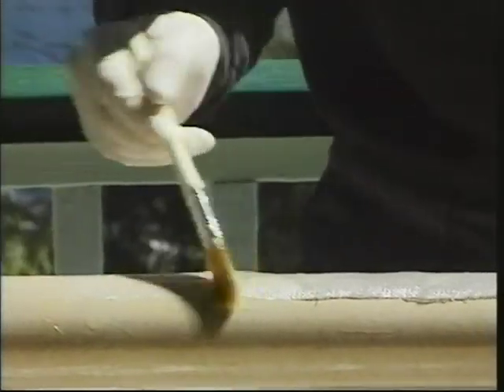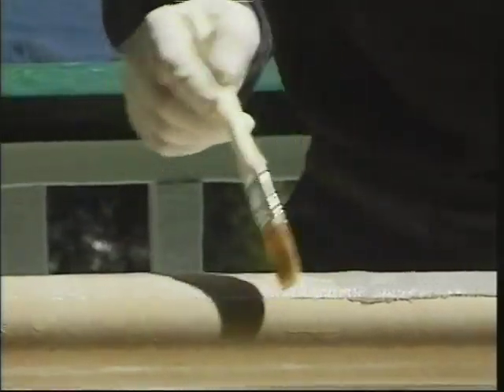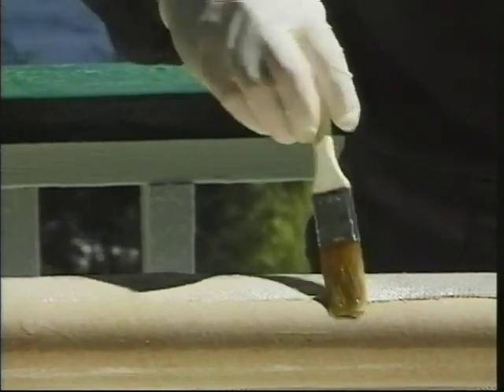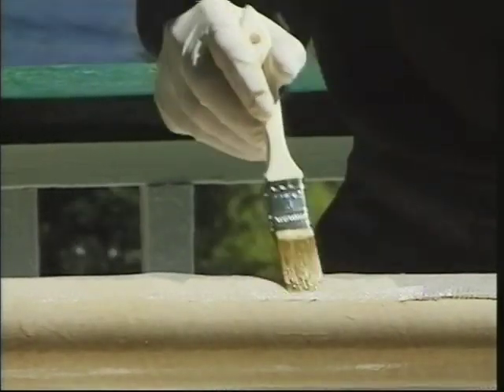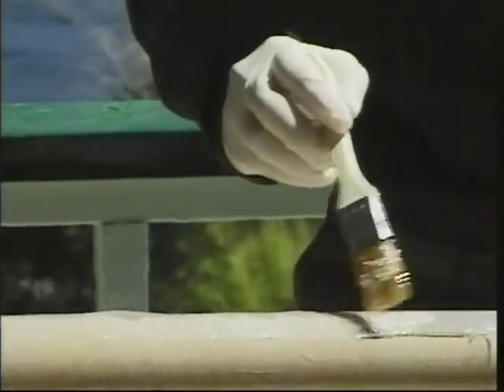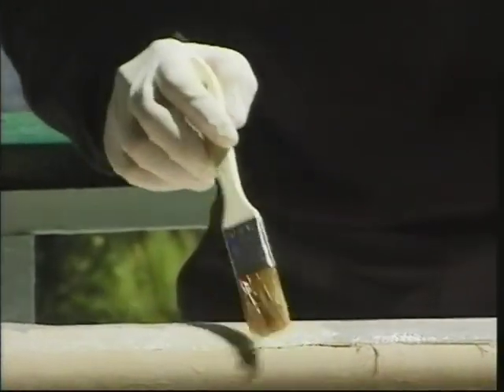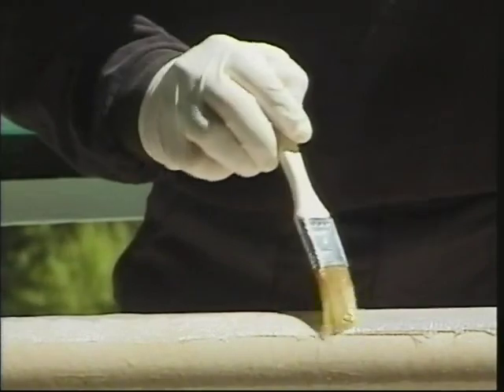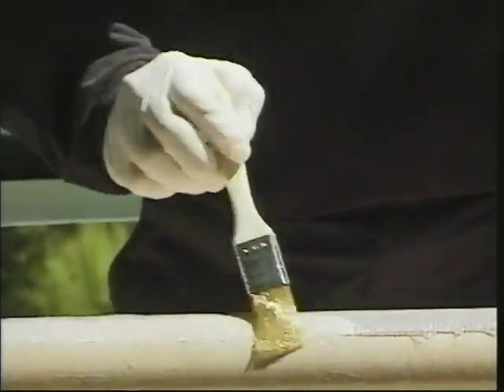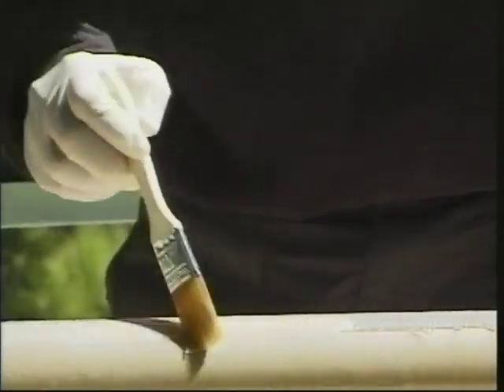And it's saturating that cloth and getting it well impregnated and filled with the resin. You want to get this edge stuck down real well so that when you come back around on your second wrap of the tube, you don't have it sticking up at all. That'll cause a number of air bubbles to get into the laminate. And air in a laminate